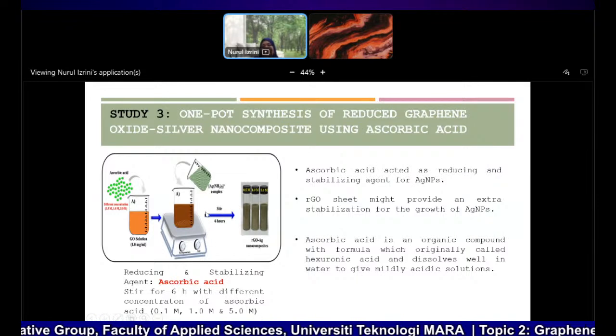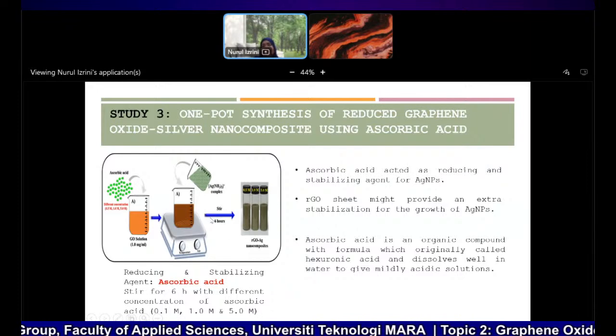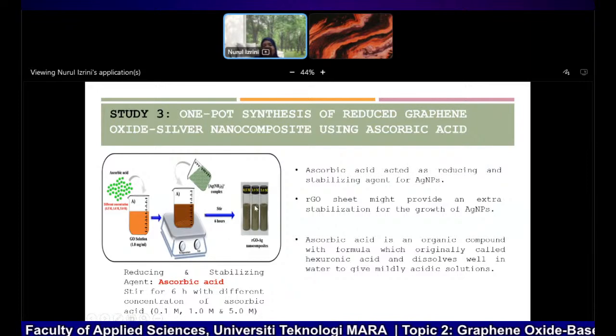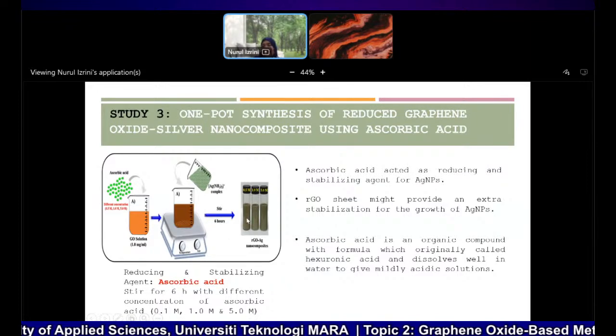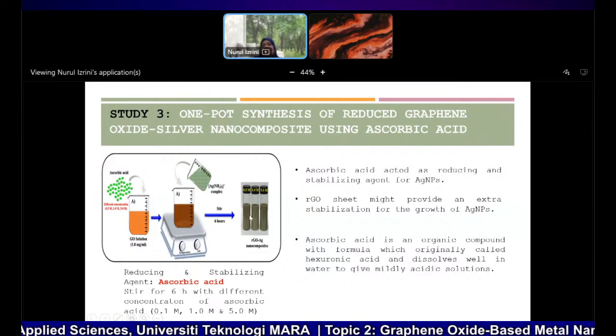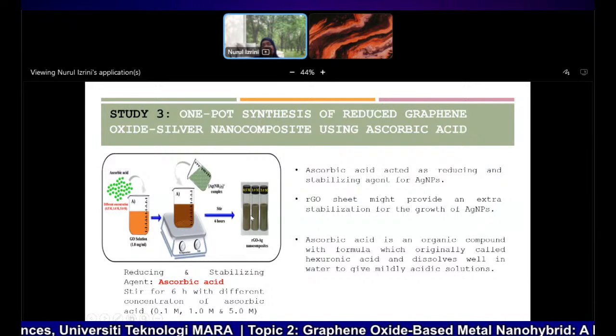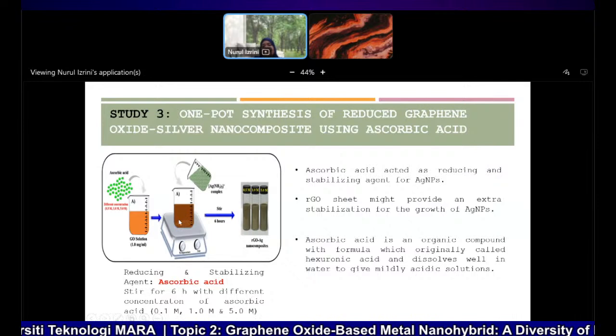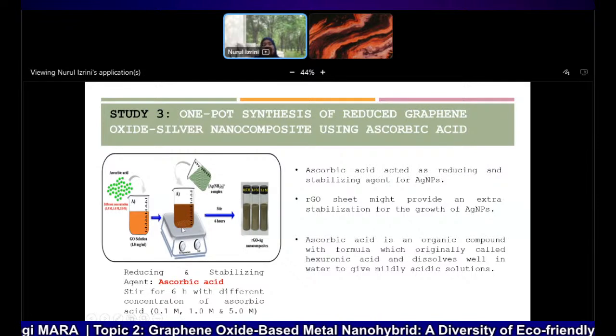This takes only 6 hours of stirring, and we used different concentrations of ascorbic acid to know which concentration gives good formation of Ag nanoparticles. This is the same method, just using stirring without any heating.